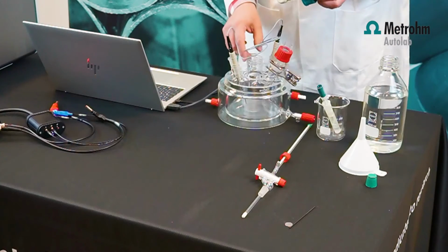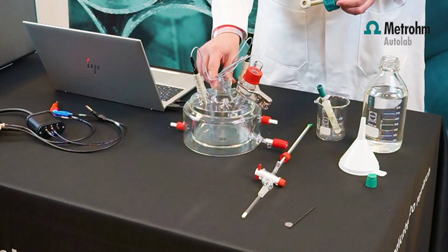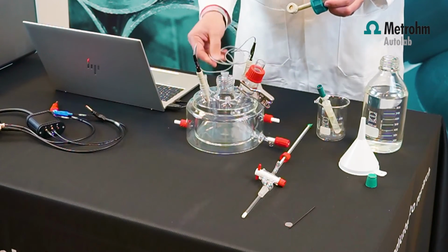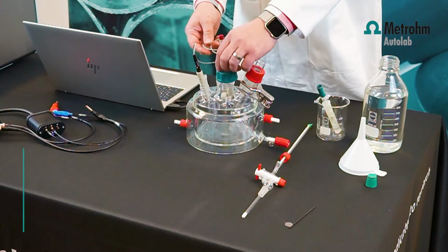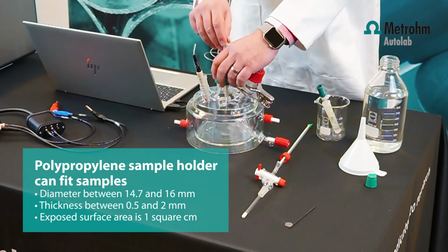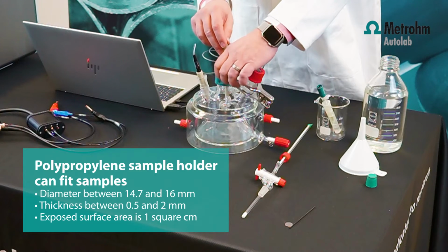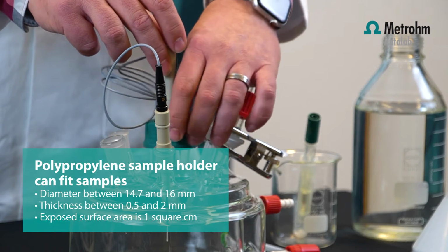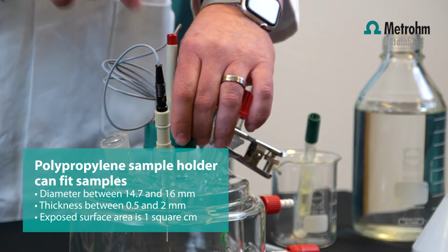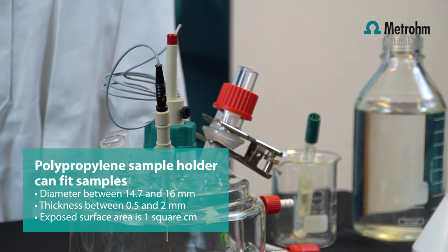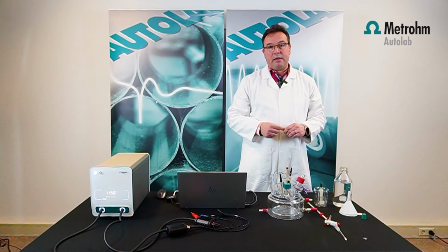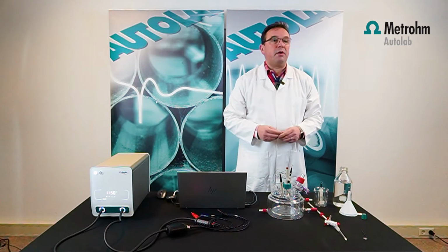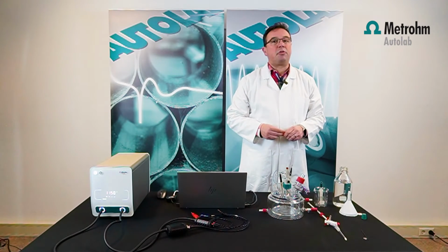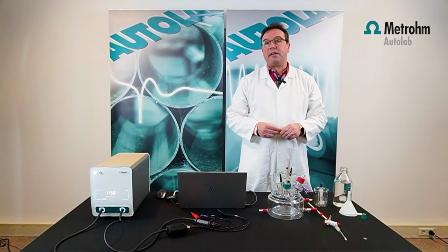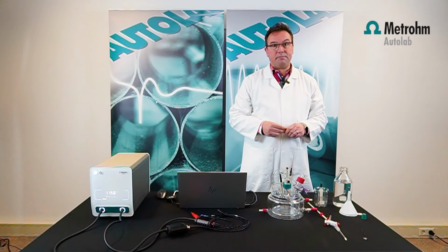Okay, go back to the corrosion cell again. So here's my corrosion cell. I can insert, it's a polypropylene sample holder, and it can fit samples between 14.7 and 16 millimeter in diameter, and a thickness between 0.5 and 2 millimeter. The exposed surface area is going to be 1 square centimeter. This is a lightweight, low friction and wear resistant material with good physical and processing properties and capable of operating in temperatures more than 90 degrees centigrade.